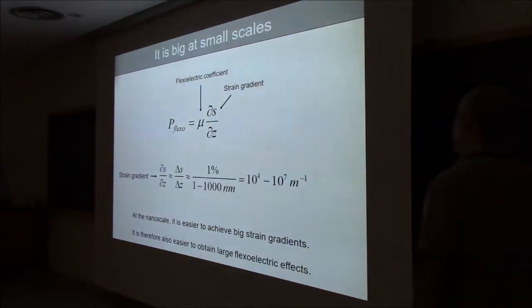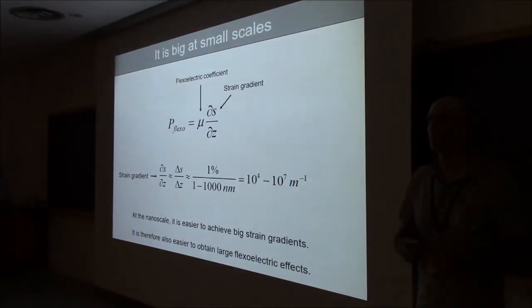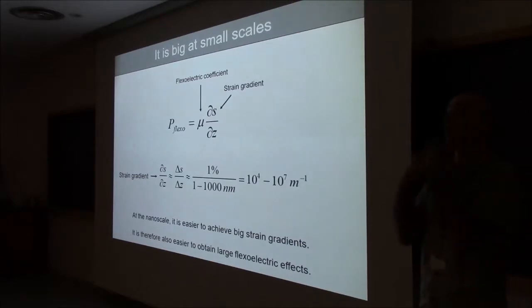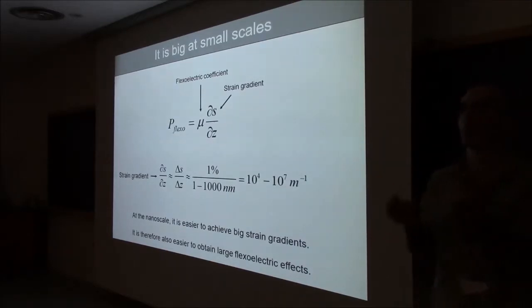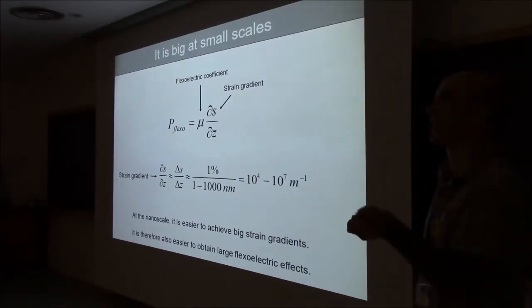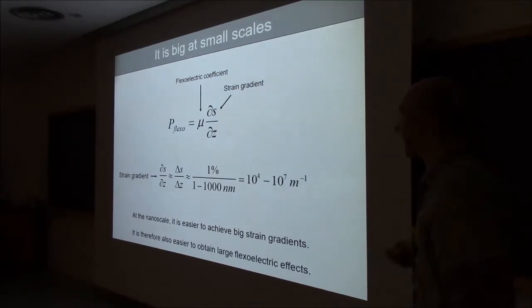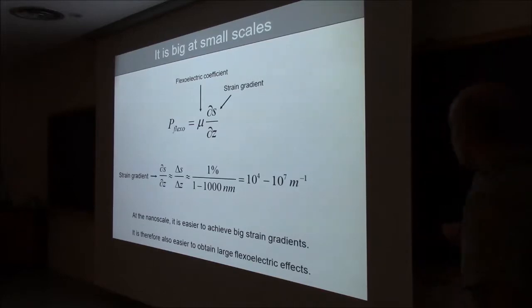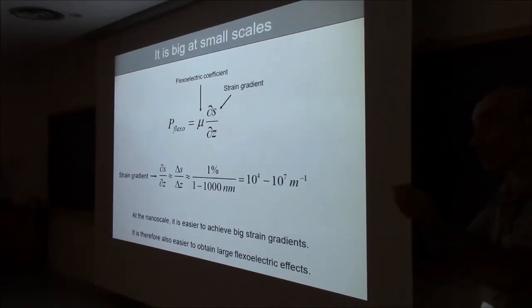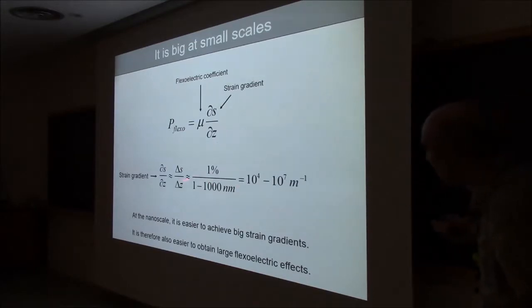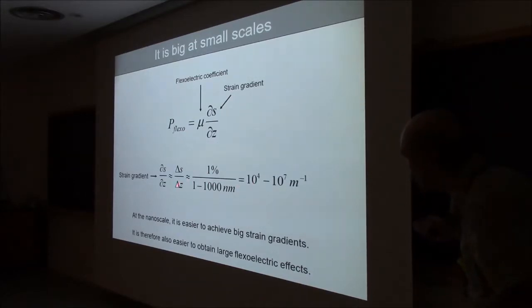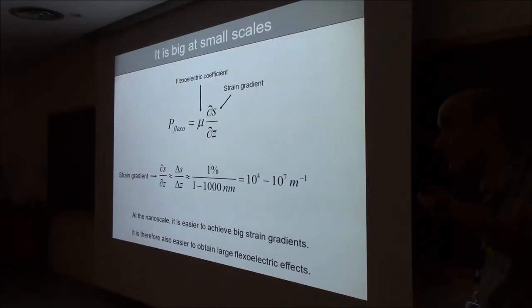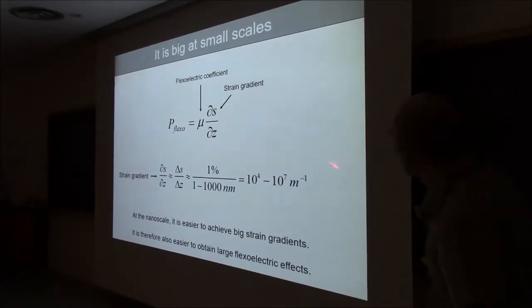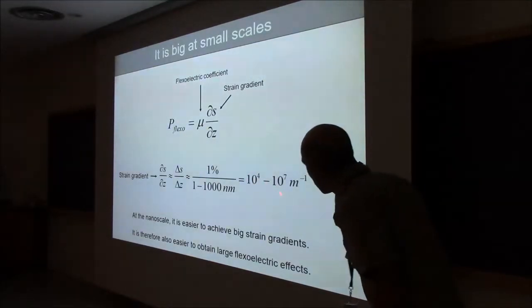Okay? So if you try to bend a ceramic, if you try to make a deformation in a ceramic, typically the maximum deformation that the ceramic can withstand before it breaks catastrophically is of the order of, say, about 1%. Now this 1% maximum deformation that you can get, if you divide it over a relaxation length, which is between 1 and 1,000 nanometers, okay, definition of nanoscale, it gives you a number between 10 to the 4 and 10 to the 7.